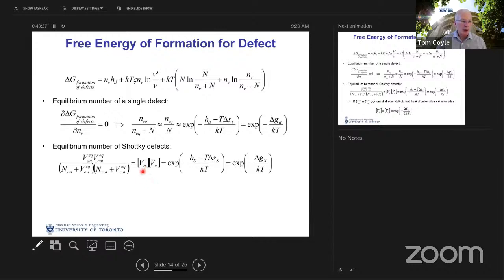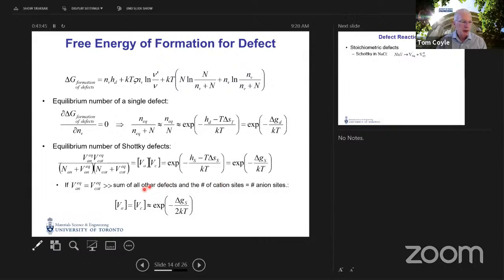We can only find the mole fraction of anion vacancies by assuming that the number of anion and cation vacancies is equal. That's true of Schottky defects if no other defect creation mechanism is important. If cation or anion vacancies aren't created in significant numbers by any other type of defect reaction, then we can assume that the numbers of those two defects are equal, and therefore that the lattice fraction, atom fraction of anion vacancies is equal to the fraction of cation vacancies, and that then is given by this exponential with a 2 in the denominator.